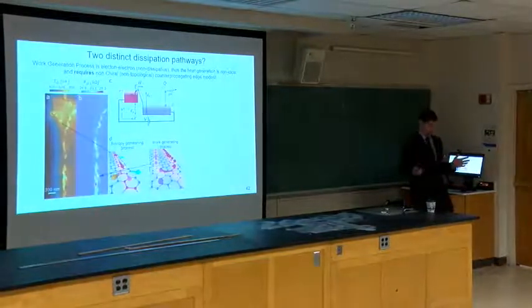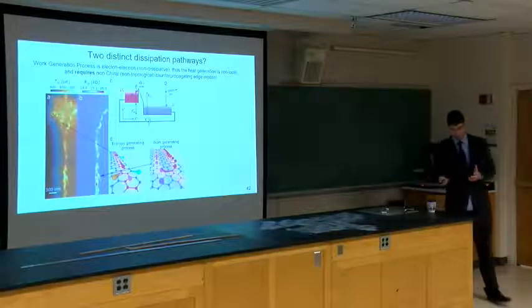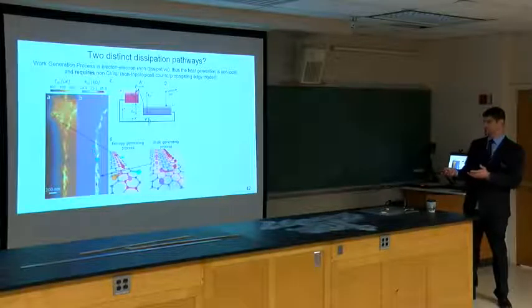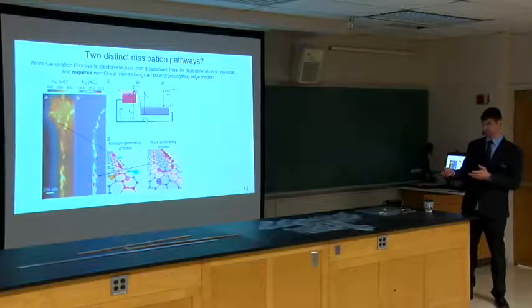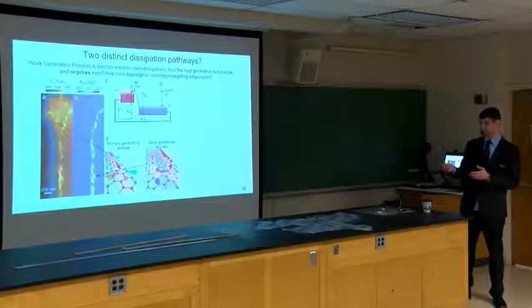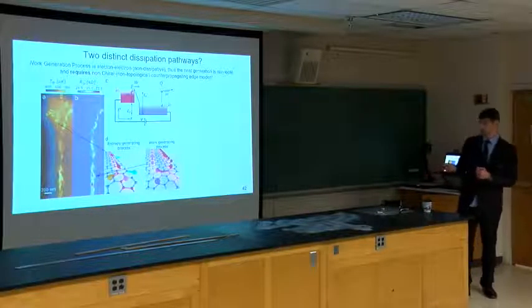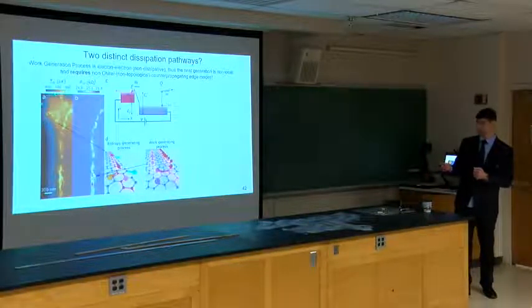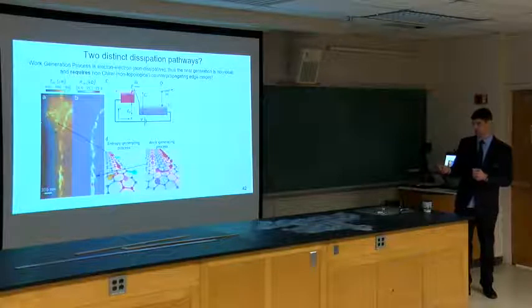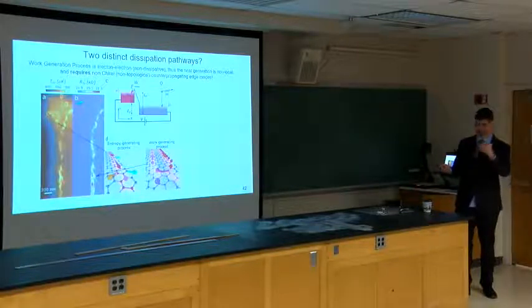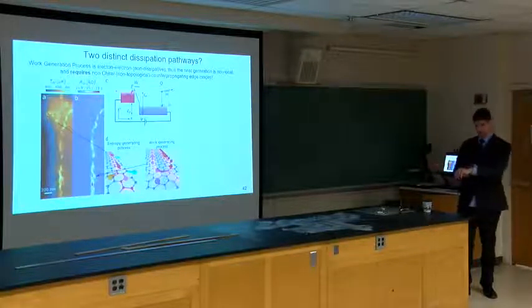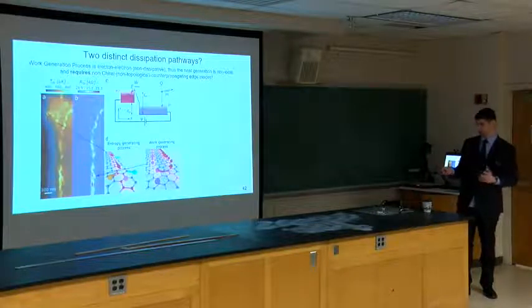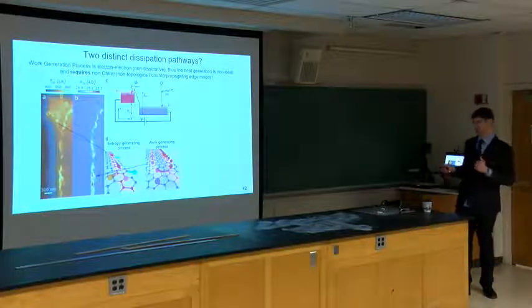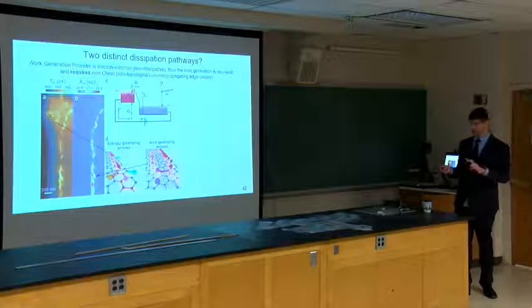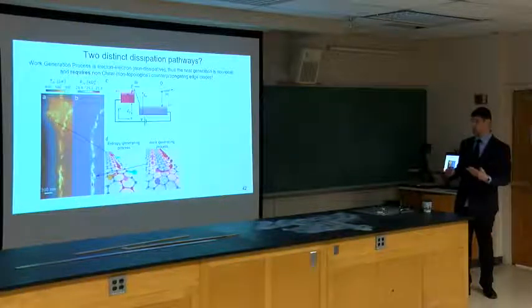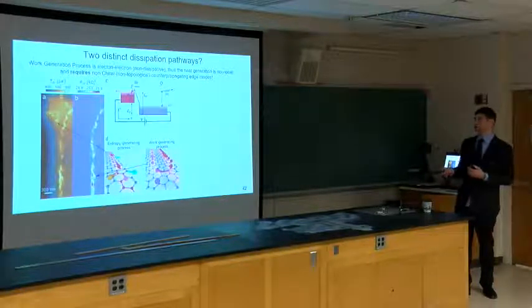So what's happening here? Well, we have 2 pathways. If we look at the scanning gate signal, and this is the area that I showed before, and then we compare it to the thermal signal, we see that, first of all, there's heat on the edge, but there's also this kind of rounded ring that shows up about 200 or 300 nanometers inside. So there's 2 mechanisms that we propose that have to occur in order to explain this.